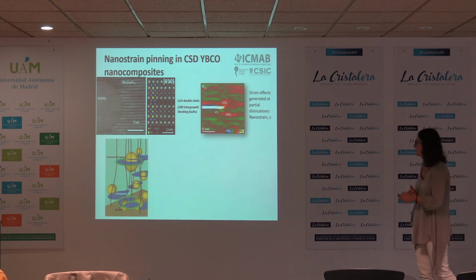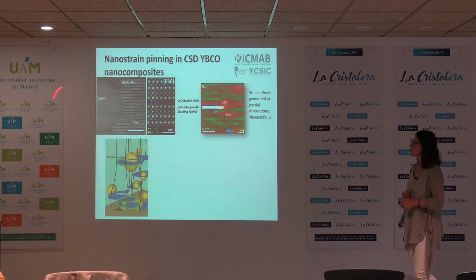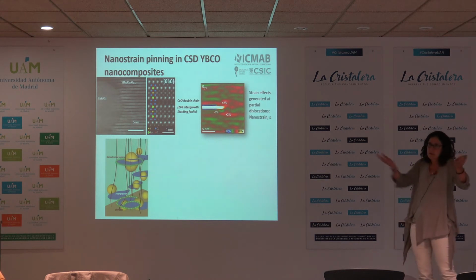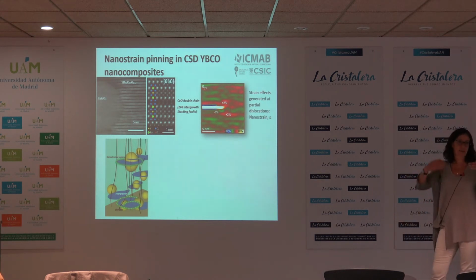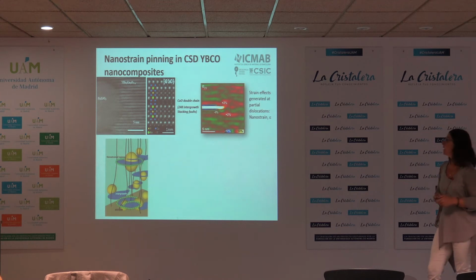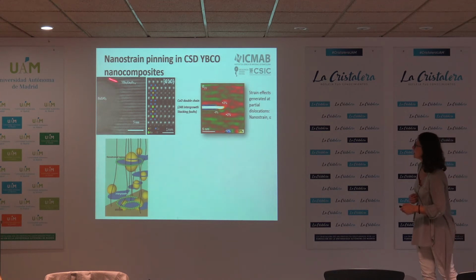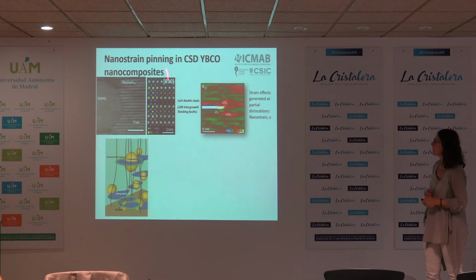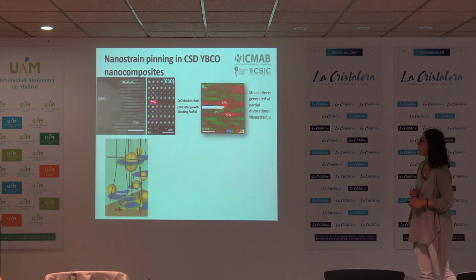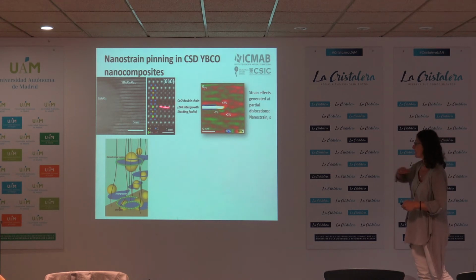In fact, what we see is that the system doesn't like to have these random nanoparticles in the epitaxial layer, and therefore generates additional intergrowths. And these are these black lines that we see here. These are that instead of having one copper oxide chain in the structure of the YBCO, we do have two. So this should be only one layer of copper oxide, and we see that we have two layers of copper oxide.